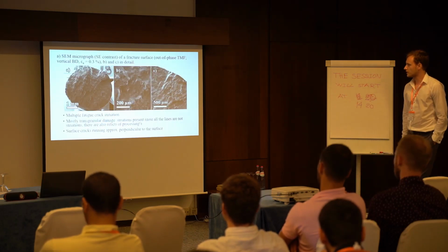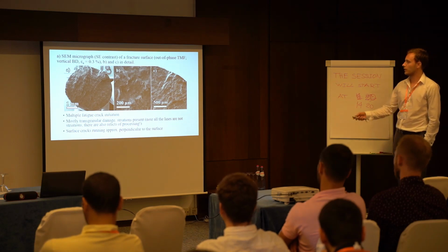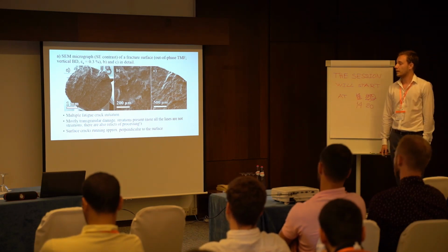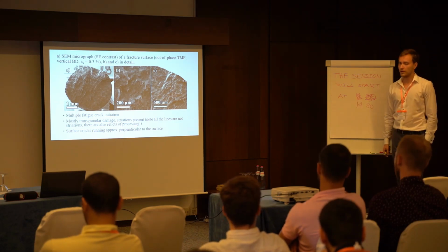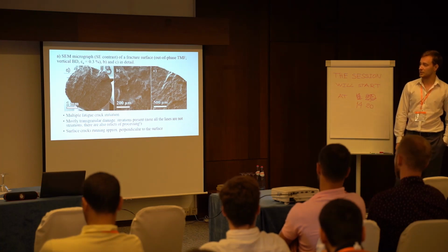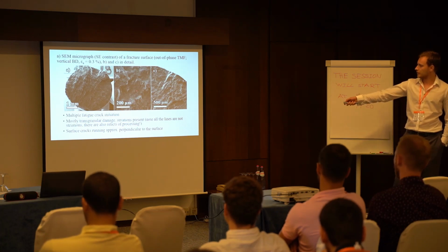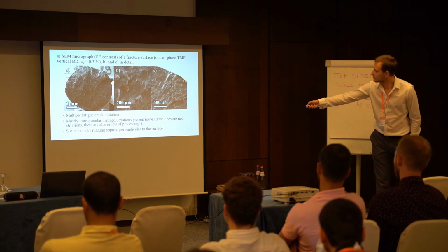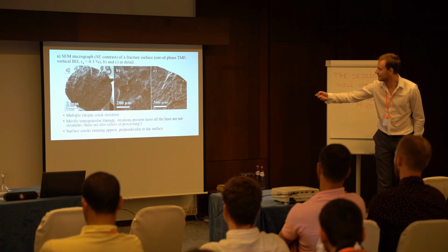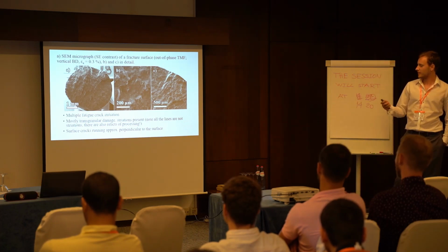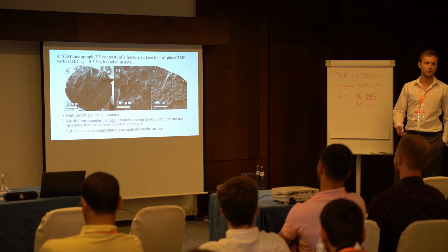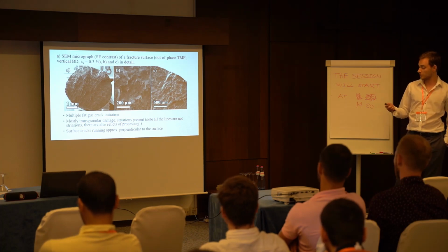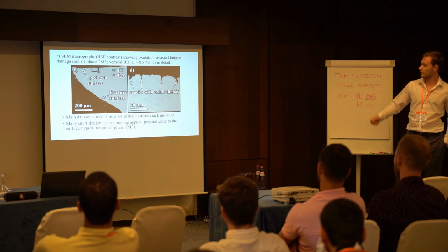Now let's take a look at what the damage mechanisms were like in out-of-phase testing. So it was different. Obviously, we had multiple fatigue crack initiations. The damage was mostly transgranular, and there were striations present. You cannot see them so well, but they are in there. You have to trust me. Surface cracks were running approximately perpendicular to the surface, which is also clearly seen here.